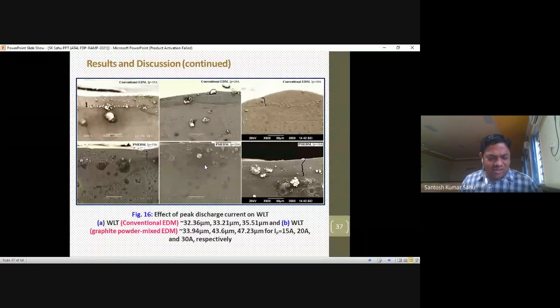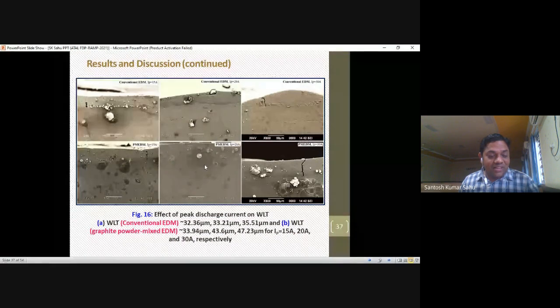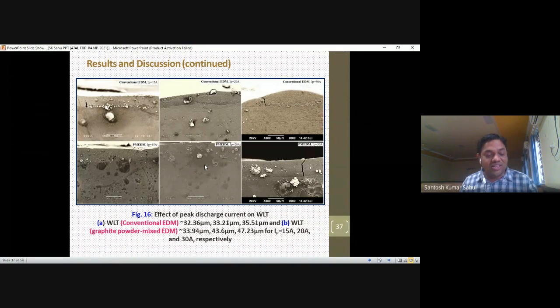So due to the dielectric fluid appearing increasingly inefficient to sweep out the debris from the machining zone, the molten metal gets re-solidified, forming the white layer that adheres onto the machined surface. Thus, the white layer becomes thicker and thicker as the discharge current is increased gradually. Since during powder mix EDM the graphite powder, owing to its thermal conductivity, carries a percentage of the discharge heat energy, it was expected that the surface finish would be appreciably higher.